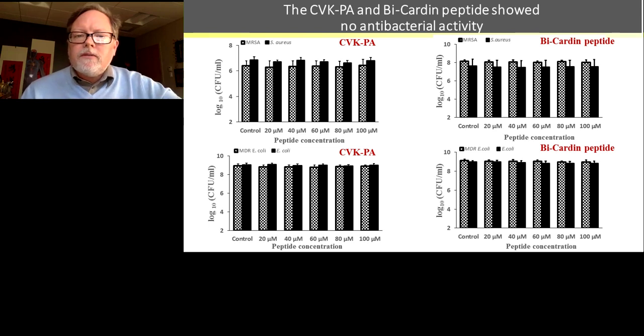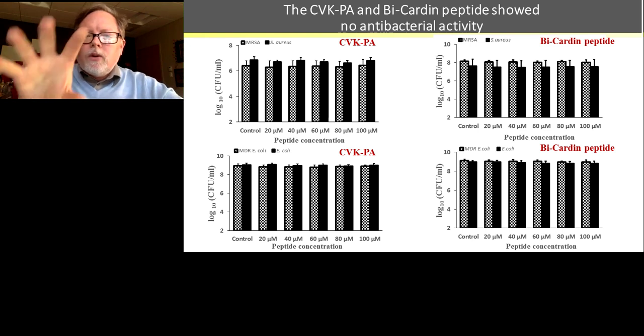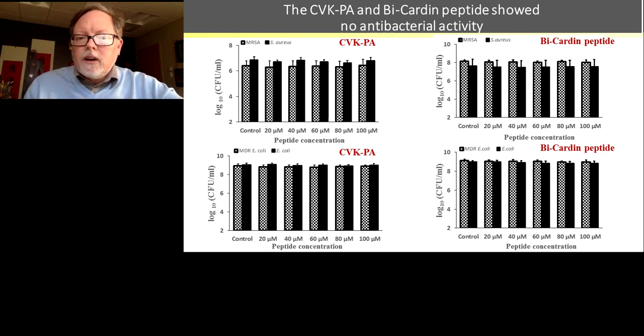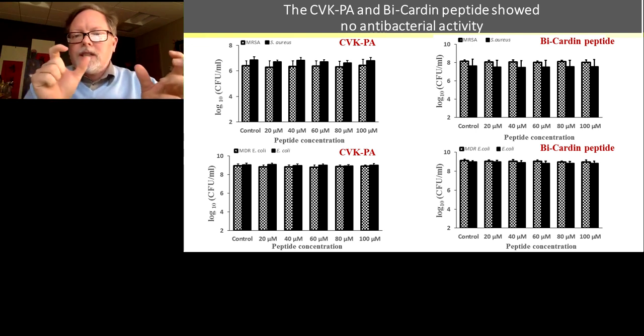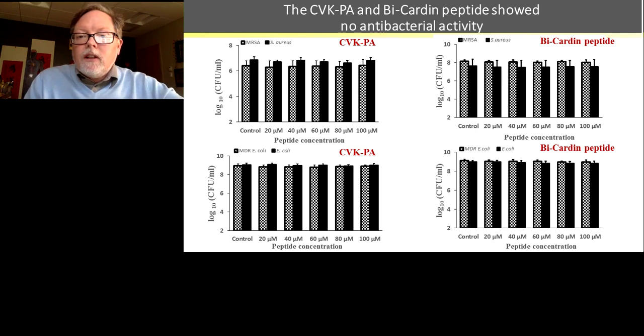But here's the part that I mentioned before. You need each part of this self-assembled molecule to work. On this slide are the building blocks by themselves, not the collective molecule, but just each building block. The Bi-Cardin peptide, the peptide amphiphile, they don't work. The y-axis here is the number of colony-forming units. It's the same, no matter what concentration you use. So only when you have the combination of the beta-forming sheet, the Bi-Cardin peptide, and the hydrophobic backbone do you get that fiber to then kill the bacteria. So that's a real definition of nanotechnology. It has to form a nanostructure.